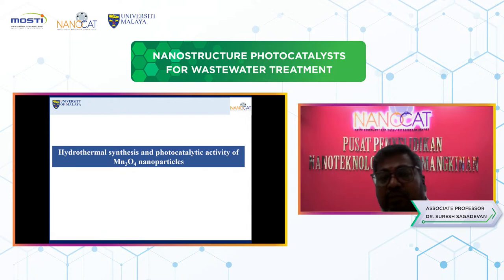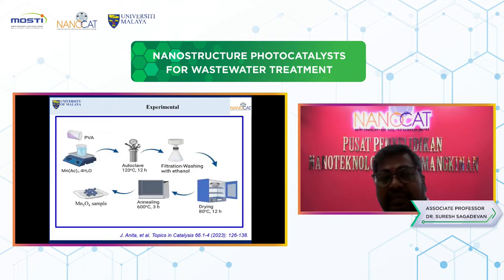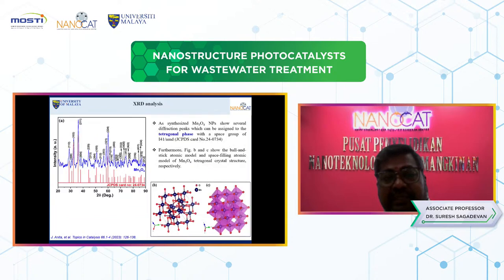And then Mn3O4, the next material, using hydrothermal synthesis. We used manganese acetate tetrahydrate and PVA mixed together, and the solution was taken into the autoclave at 120 degrees Celsius for 12 hours. After filtration, washing with ethanol and drying at 80 degrees Celsius for 12 hours. And then again, we went for calcination. We got the Mn3O4 nanoparticles. You can look at the XRD patterns we obtained for many peaks, the several peaks,